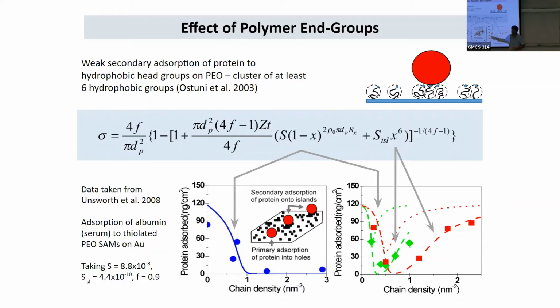But most of the examples we picked, preliminary protein adsorption studies, are done with spherical proteins like albumin because those are the most abundant ones in your blood, right? Casein, albumin. And so, yeah, these studies were done with these spherical proteins. So it worked out fine. You're right. I mean, if it's a much more complex protein, then things will happen. So it's just radius of gyration that is the only parameter? Yeah, and the radius of gyration is also experimentally known, at least for polyethylene glycol. You have a nice, beautiful plot that people have made of radius of gyration with the number of monomers.